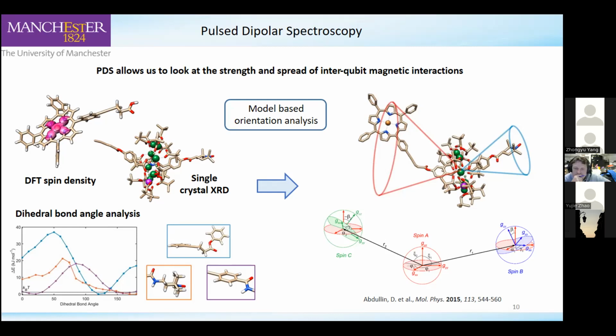We did have a look at sampling a very big conformational space, but we were able to narrow that down based on both the fits not being that great and the DFT suggesting that there's really only a small bit of moving around. So at the end, you had this conical rotation model, basically. Or was it still the distribution of the dihedral angles of simulated traces? So you checked it with the dihedral angle, but then you simplified the model to conical rotations? Yeah, effectively the DFT was guiding us, but the conical model is so we sample enough of the space to see if there is another conformation in there that hasn't been picked up by the DFT. We wanted to sample a wide enough space to make sure we weren't missing anything.